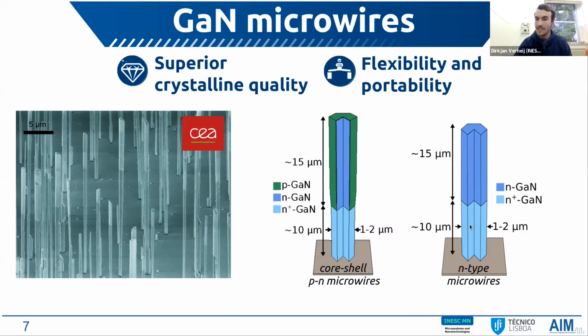wires which are entirely n-type doped. So we have the bottom part which is heavily n-type doped, and then the top part which is moderately n-type doped, and these doping concentrations are a consequence of the growth process. And then here we have essentially the same sort of wire, but around the top part of the wire, a thin p-type gallium nitride shell is grown, which creates a p-n junction in the radial direction from this point to the top of the wire.